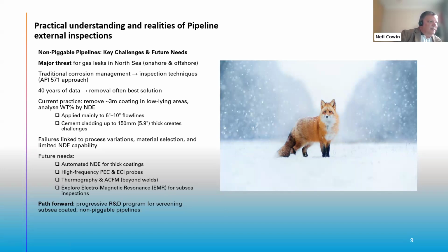that would be one of my top of the line requests to the industry, if it was physically possible, because all we're basically doing is taking topside NDE equipment and encapsulating it into pressurized containers, and the probes run automatically, driven by an ROV and an umbilical back to surface ships, which they're launched from, to go onto deeper water pipelines up to about 250 meters at the moment.